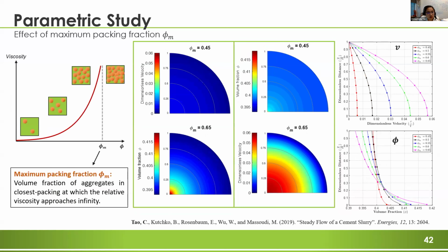So here is another parametric study result, detecting the effect of the maximum packing fraction. It means the volume fraction at which the viscosity approaches infinity. As Phi increases, the velocity tends to increase, and more particles tend to concentrate at the center. And from the figure on the right, we can see that both the velocity and the volume fraction distributions become more non-uniform for larger values of the maximum packing fraction, which indicates a higher packing.